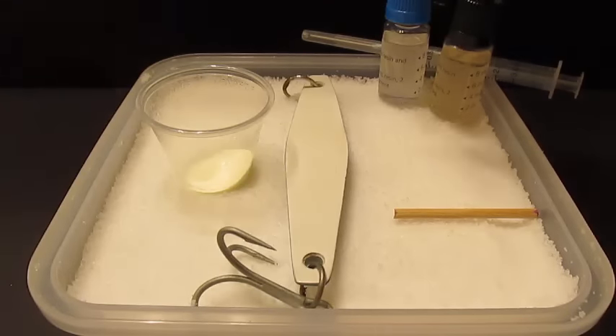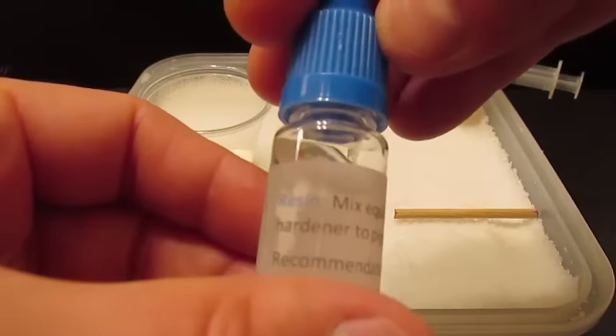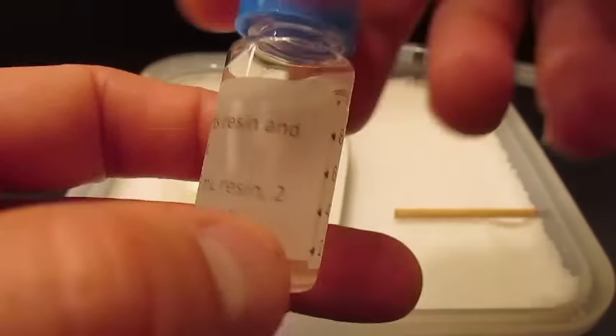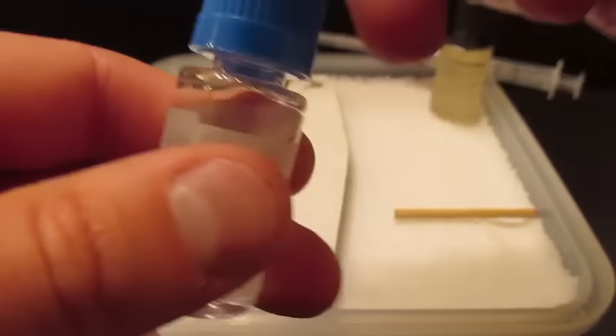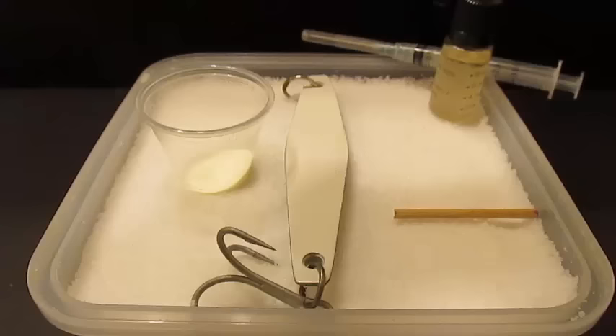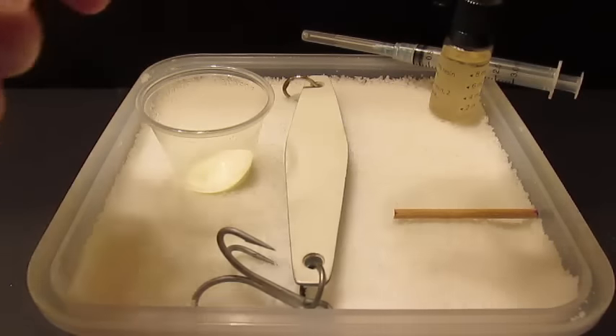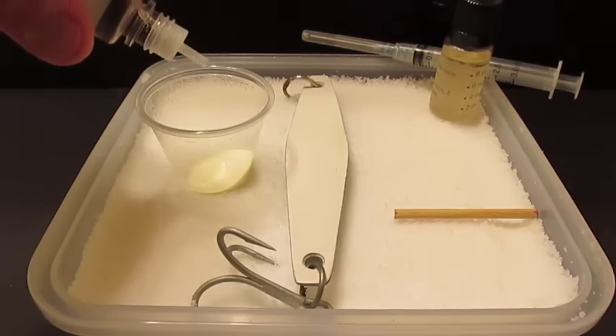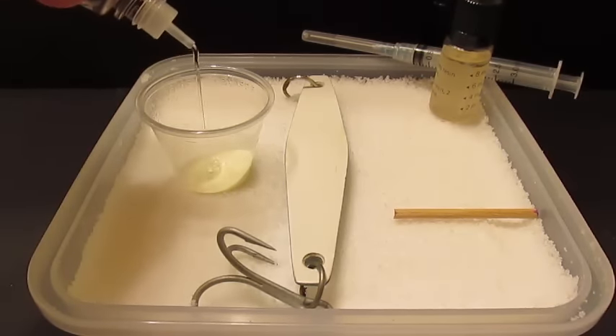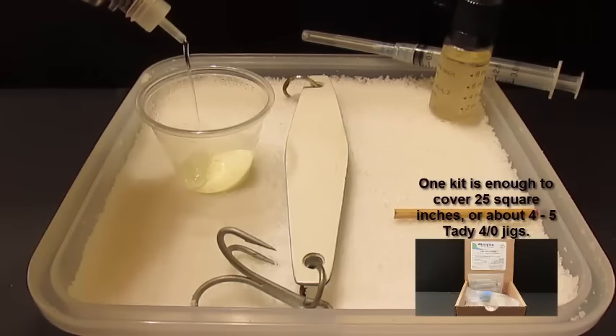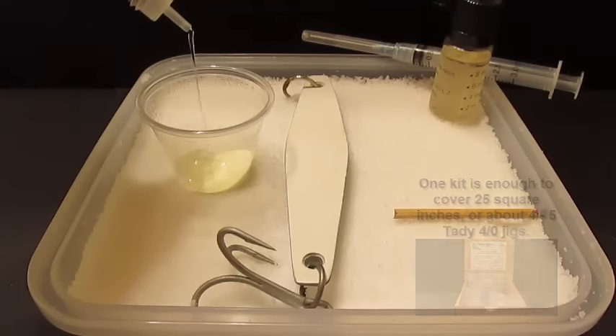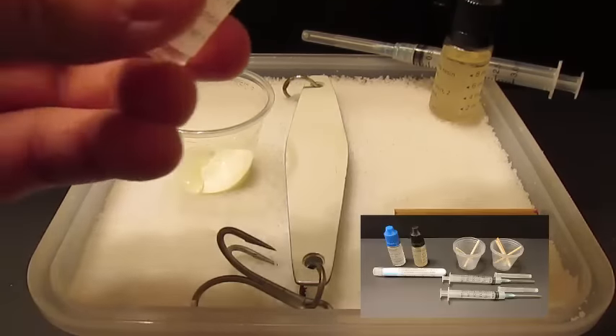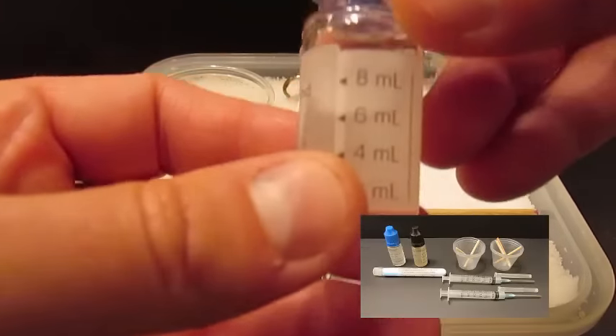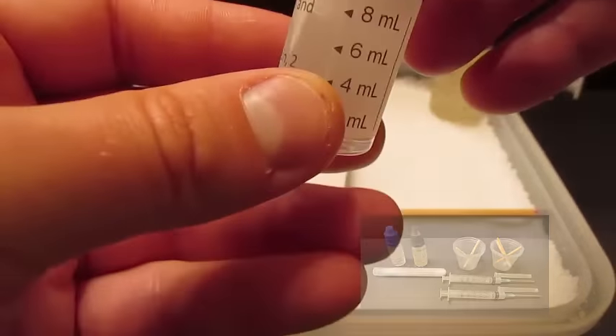The order in which you add materials does not matter, but you generally have about 15 minutes to work with the material once all the components are mixed together. After about 15 minutes, the material becomes increasingly viscous and will start to cure. Use the mixing stick that comes with the kit to mix the material. Try not to crush the pigment during the mixing process. Just mix it well enough so that it gets homogenized.